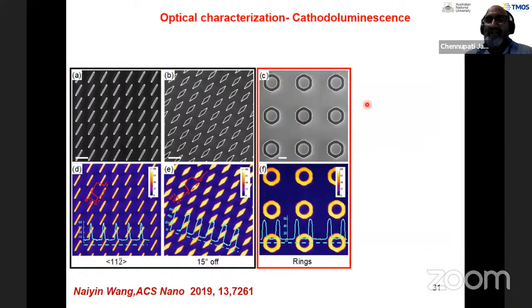So Naiyin Wang has taken these structures and looked at the cathodoluminescence from these structures. Here's the top view of these nanomembranes, nanodiamonds, and nanorings. And in the case of cathodoluminescence, instead of using lasers, we use an electron beam to excite the electron hole pairs and look at the light coming out of these.